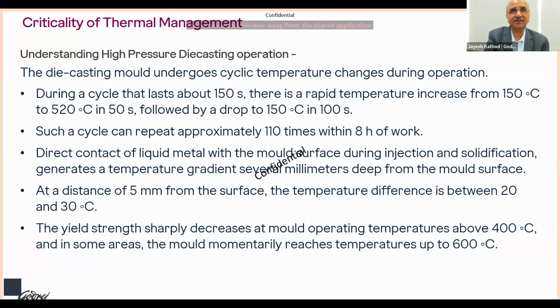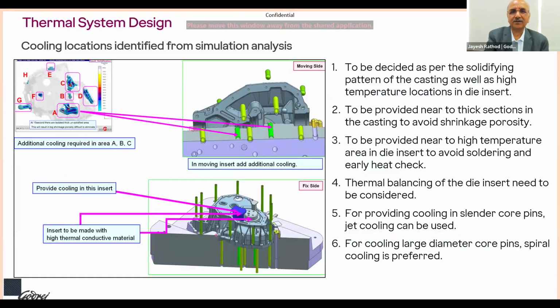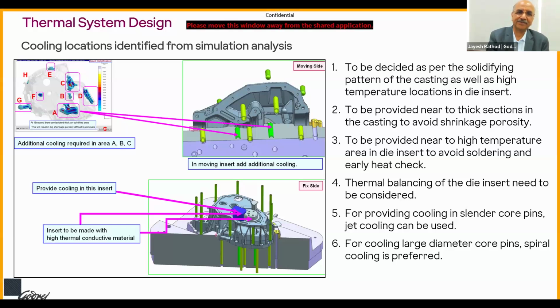When the tool steel comes in contact with the very high temperature of the aluminum material, the temperature increases on the surface, and on the core the temperature is not passed on as much. Because of this, there will be compressive and tensile stresses in the same section of the die, and because of this it is affecting the die life. So as a tool maker, what we do is we understand the impact of the thermal cycle on each die element. We design the thermal circuit by taking help of empirical formulas and also validating through simulation software.